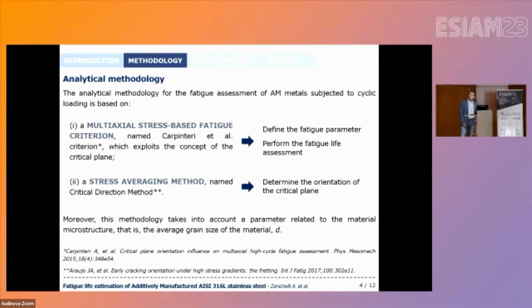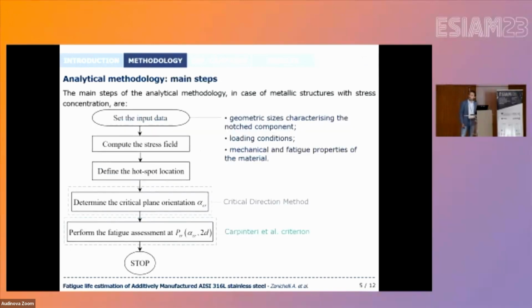Moreover, this methodology takes into account a parameter related to the material microstructure, that is the average grain size of the material, which is named here D. Here are shown the main steps of this methodology in the case of metallic structures with stress concentrations. In particular, firstly, some input data need to be set, that is the geometric sizes characterizing the notched component, the loading conditions, and the mechanical and fatigue properties of the material. Then the stress field is computed within the structural component, and the hotspot location is defined on the surface of the component itself.